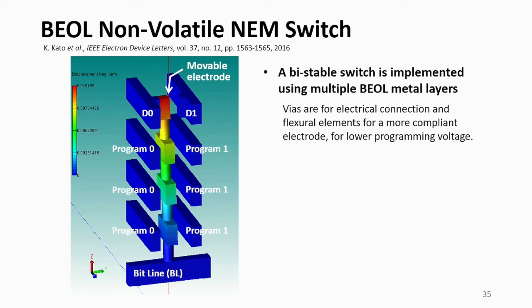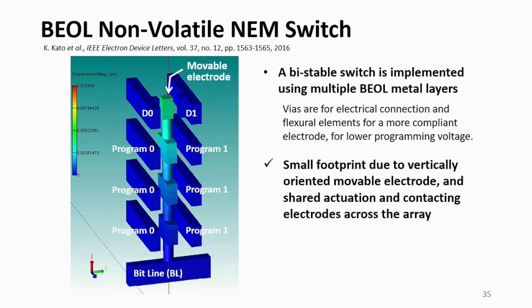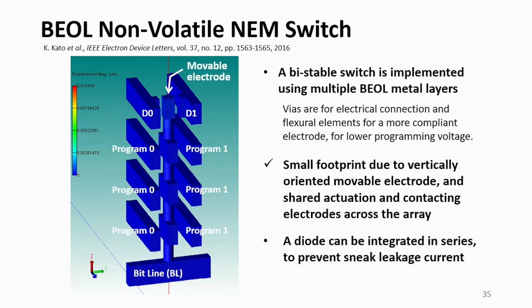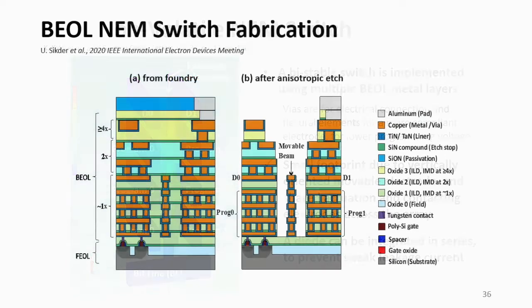Now imagine that you have a 2D array of these reconfigurable switches, and the data electrodes can be running all along the one direction in the array, as well as the actuation electrodes, and the bit line at the bottom there runs in an orthogonal direction. This switch has a much smaller footprint than the switch I showed you earlier, and because it's vertically oriented, you can easily integrate a diode at the bottom of the switch to force current to flow only one way through that movable electrode. So how do we fabricate this?